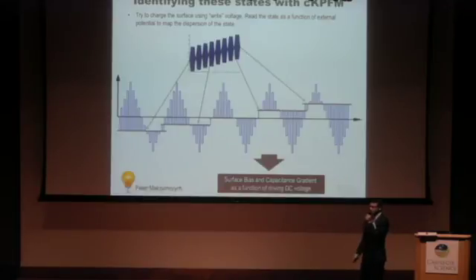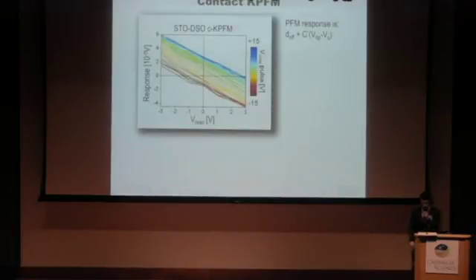And so what we hope to do by this technique is to look at the dispersion in the polarization states as a function of these DC voltages. If we take a standard material like strontium titanate as a thin film on dysprosium scandate, this should not be ferroelectric. And indeed, when we look at this response, you can see all straight lines, which suggests that this is purely electrostatic response. But let me walk you through what this diagram actually means.